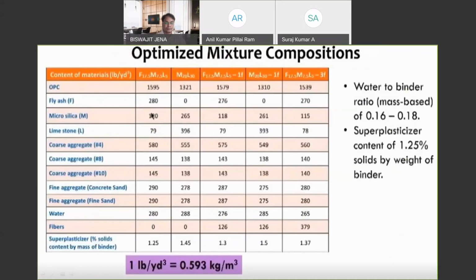So here is the final mixture composition. I use the selected aggregate combination that I showed: 40%, 10%, 10%, 20% by mass of all these aggregates, and two different paste mixes. One with fly ash, micro silica and limestone, and the second one with limestone and silica fume. So two different mixes, with and without fibers, with a water cement ratio of 0.16 to 0.18, and a superplasticizer dosage of 1.25% by weight of the binder, that is about 5% by weight of all the powders, including the liquid content of the superplasticizer.